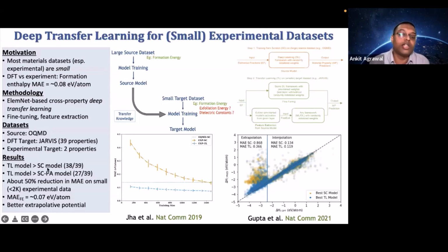That is if the scratch model is built only on elemental fractions, the blue curve that I showed before. But if the scratch model is allowed physical attributes, that library of attributes, then we are making the scratch model more powerful, while the transfer learning models are still using only elemental fractions. So this is a more stringent test, where we are giving some advantage to the scratch model. But even in that case, the transfer learning model was able to beat the scratch models in more than half of the cases.